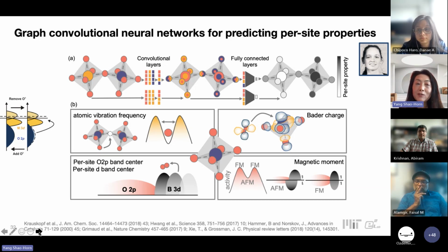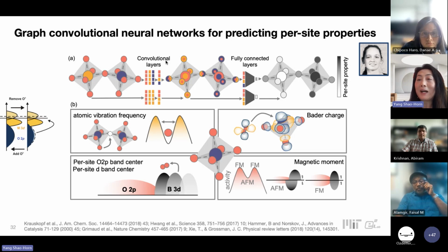You can also tune the specific electronic structure of the oxygen. So, inspired by knowing oxygen is the active site for oxygen evolution, we utilize machine learning methods, specifically a graph convolution neural network, to predict the local, per oxygen site, how they may correlate with binding of oxygenated species. Generally speaking, our work is looking at the correlation of binding or average binding of species with oxygen sites for a given surface or for bulk.